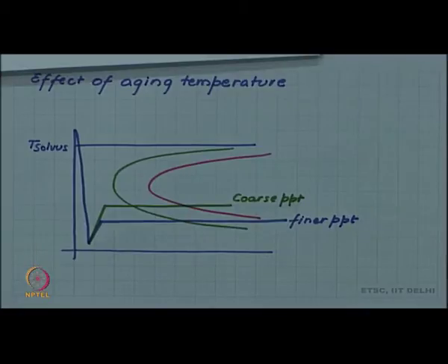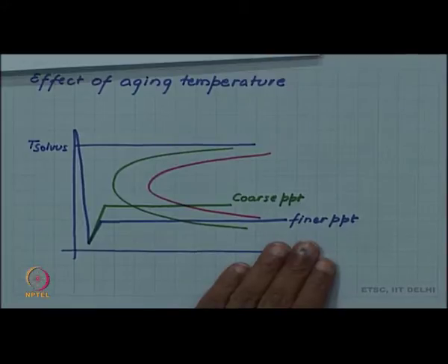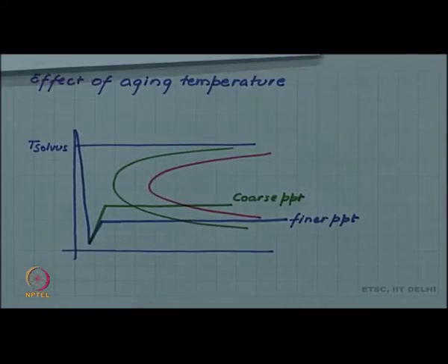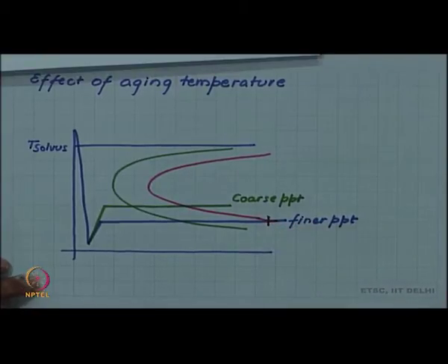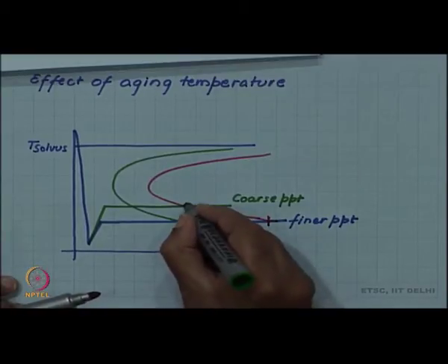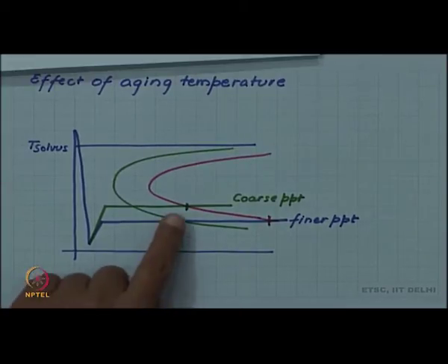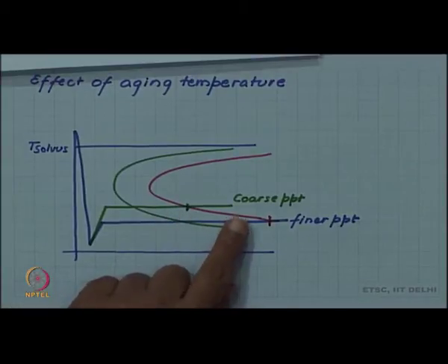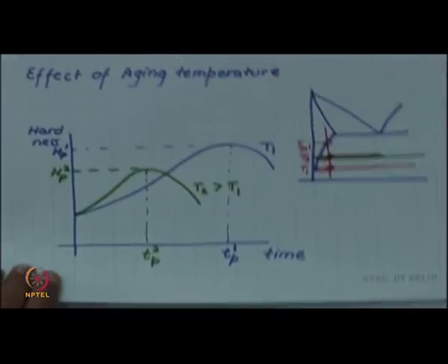So, this fine precipitate will give you a higher hardness. So, at lower temperature you will have higher hardness, but the time for completion is more at the lower temperature than at the higher temperature. So, you will achieve lower hardness at higher temperature, but you will achieve it in a shorter time.